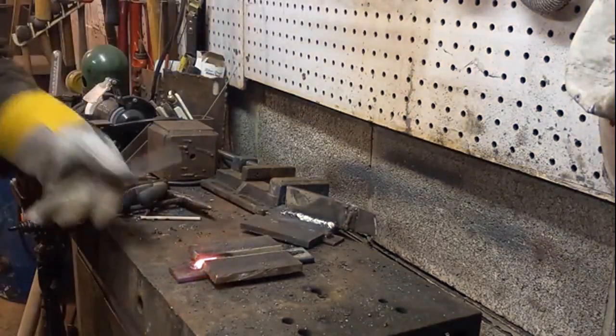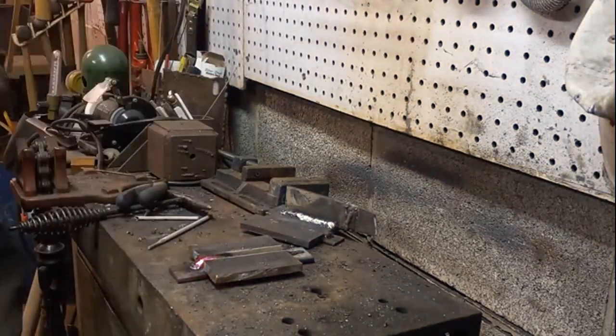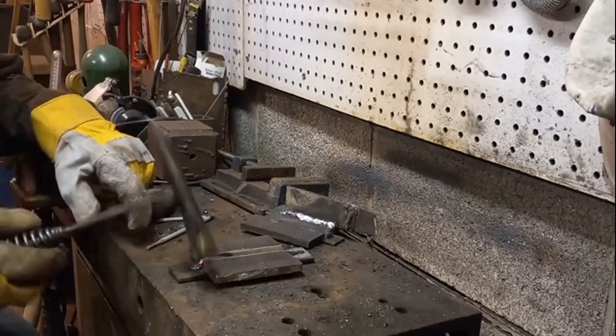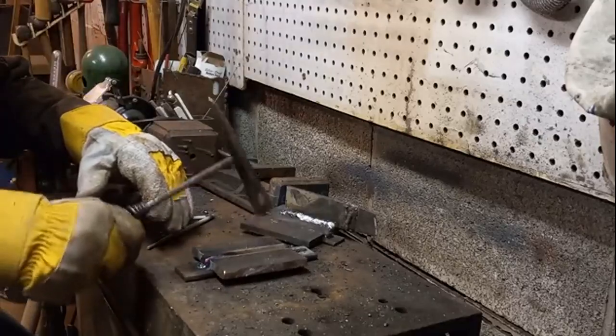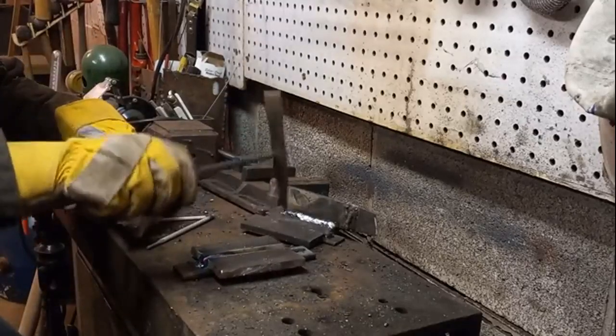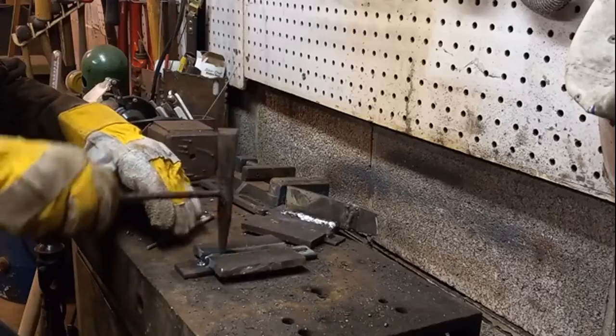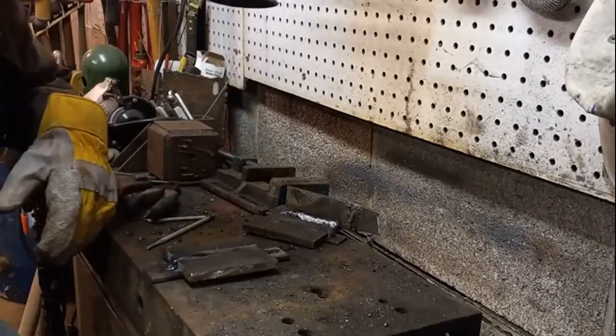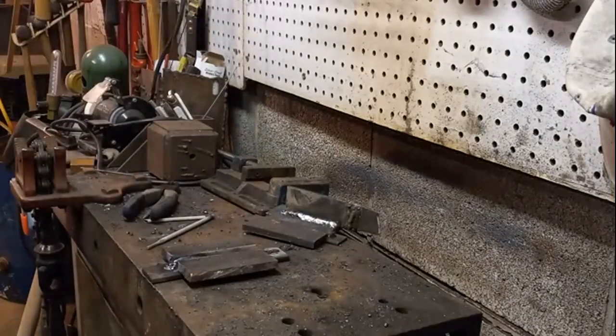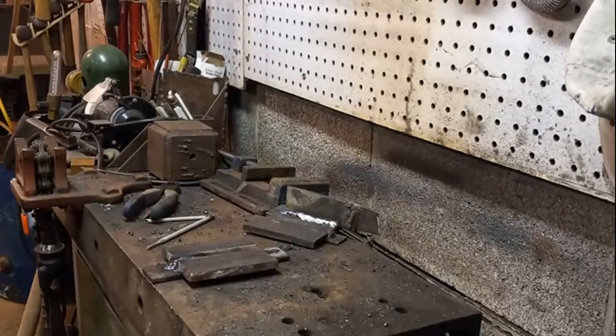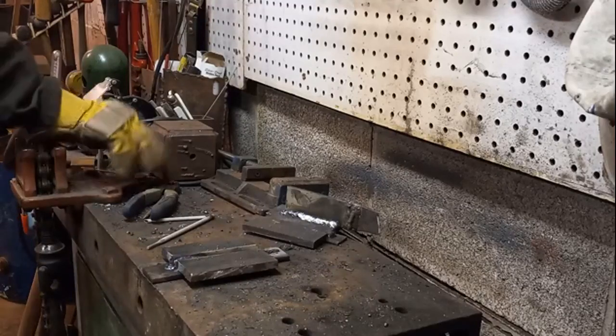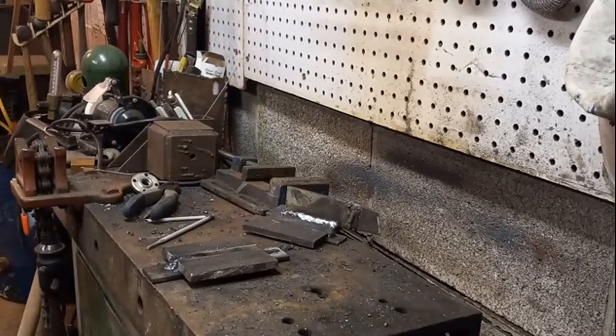To make this a little shorter, I'm going to show you the root pass, and then I'm going to pause the camera, and then I'll show you the finished product, so you don't have to sit here and watch me do everything. And that slag is not very nice. The slag is a lot like the E6027 slag. Just under the surface is like a hollow lattice-like structure with air bubbles. It's really crunchy, maybe the best way to describe it. I'm going to grab a flap wheel, throw it on this, clean that off, and then move on.